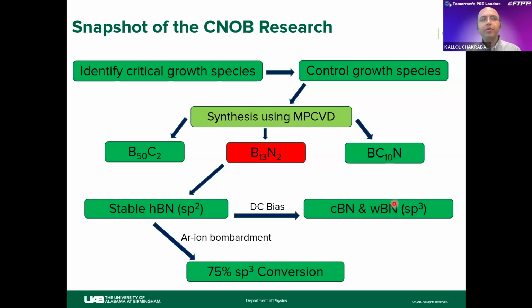Here is a snapshot of the CNOB research. We successfully identified the critical growth species from our plasma, and we are able to control our growth species by changing different parameters such as microwave power, chamber pressure, gas flow rate, and substrate temperature. We are able to synthesize the superhard materials we wanted to synthesize - those were B50C2 to BC10N.